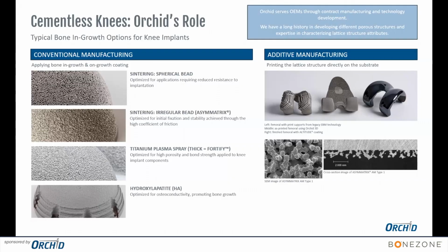So coefficient of friction, I think, is very, very important for maintaining that early stability, right? So if you look at the coefficient of friction for spherical beads, it's typically in the range of about 0.5 or so, while for irregular beads, you can reach all the way up to 1. So essentially, the force that is needed to move the implant against bone is greater than the normal force that's applied. So essentially what you're getting is early interdigitation between the porous lattice and the bone, right? You're not relying necessarily on biological fixation right away. You're getting much better mechanical fixation.